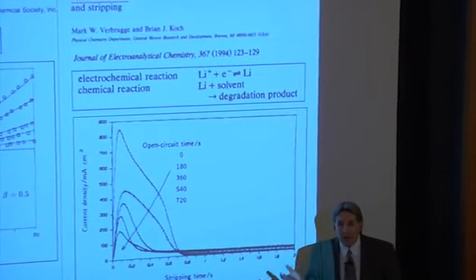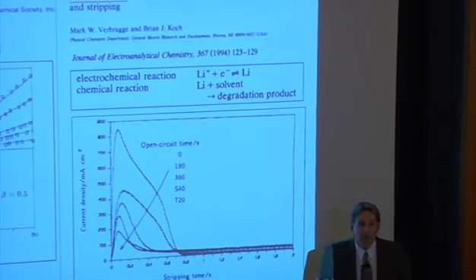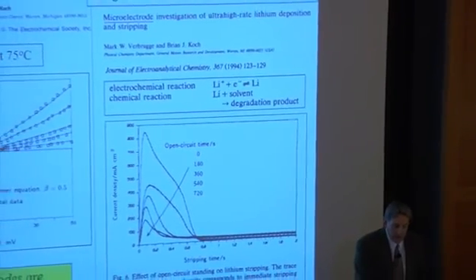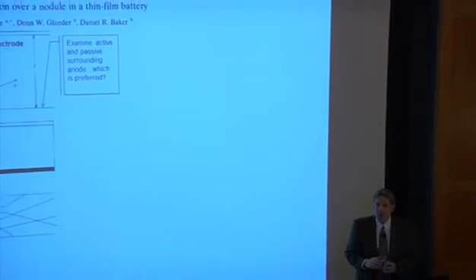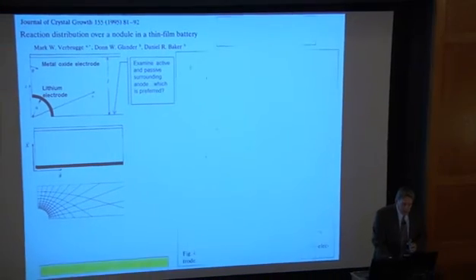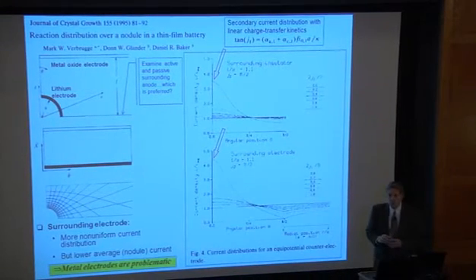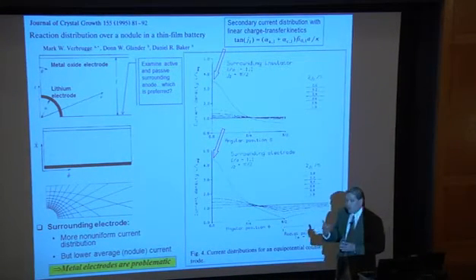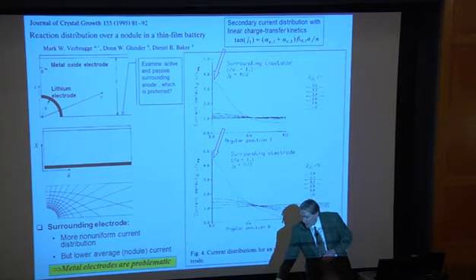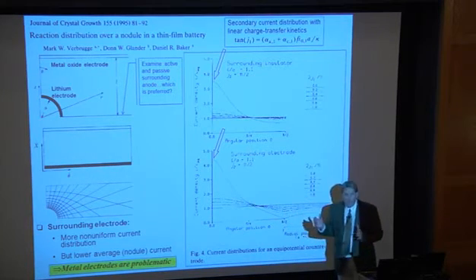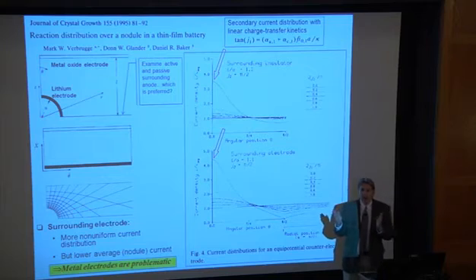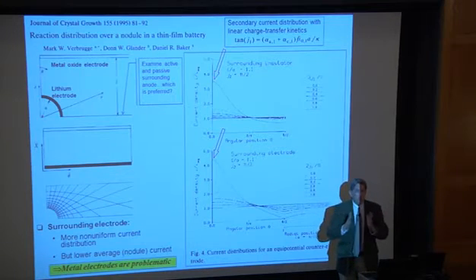And that's the problem with the lithium metal electrode. It's extremely reactive. We don't have a good solvent that, adjacent to a lithium metal electrode, shows sufficient stability. Now, one other aspect to those who deal with problems of crystal growth and nodule formation is that you do run into a paradox in a lithium-ion battery, and that is that the electrolytes are actually fairly resistant. And for that reason, we have to go to a thin film arrangement.